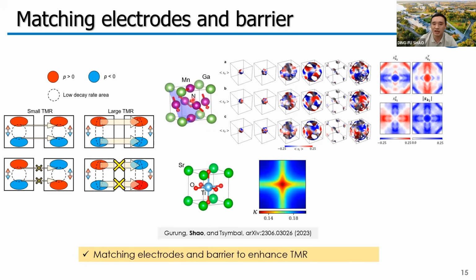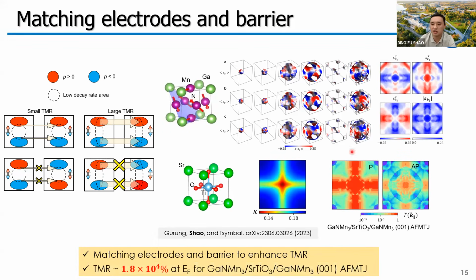So we use manganese gallium nitride as an electrode and STO as a tunneling barrier to construct a non-collinear antiferromagnetic tunnel junction and perform the quantum transport calculation. We find in the parallel state, in this cross area, we have a very high transmission. But in the antiparallel state, in this cross pattern, the transmission is significantly reduced. This generates an ultra large TMR over 10 to the power 4 percent at the Fermi level. So clearly, by matching the electrodes and the barrier, we can enhance the TMR, which is very promising to realize a readout with a large on-off ratio for antiferromagnetic spintronics.